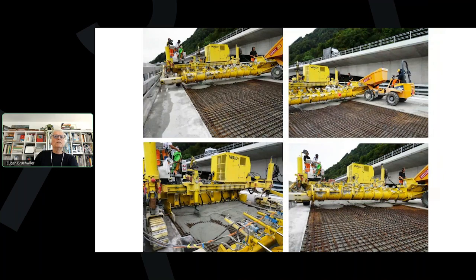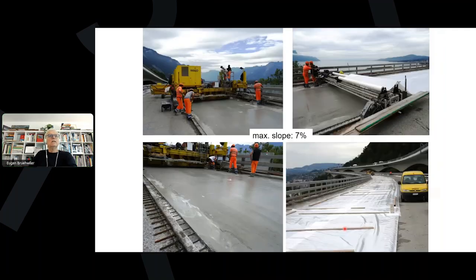where a machine has been used, like a paving machine, in order to cast the fresh UHPFRC with a thickness of exactly 50 millimeters. There is not 1 millimeter more or 1 millimeter less. We can be very precise. It's high tech. You see here also the rebars, of course, that are arranged in both directions within this 50 millimeters thickness. Here you see some photographs of what comes out behind the paving machine.